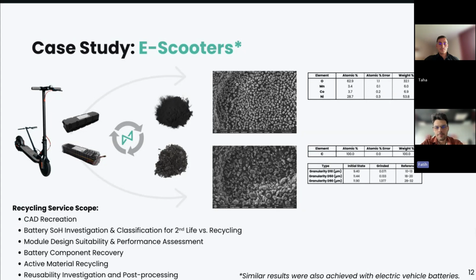And we see the composition on top from the cathode materials, so there's almost no impurity. Again, we have the NMC structure, we have the particle size distributions, and on the bottom right, we see the graphite, which was extracted in this case study. It was only graphite materials or carbon materials, and the particle size distribution from the initial state was very uniform. So we assessed that this material can be used for battery manufacturing.